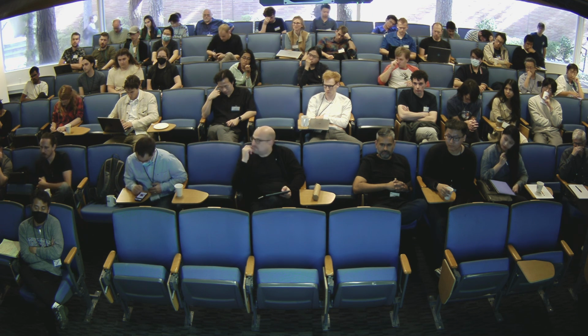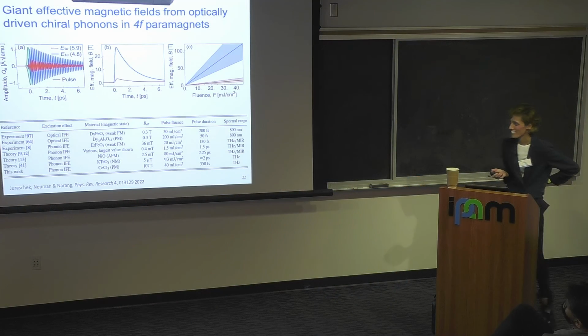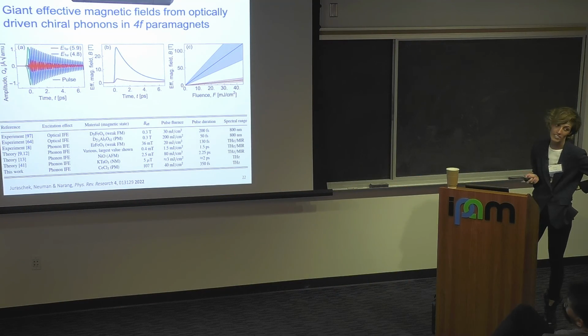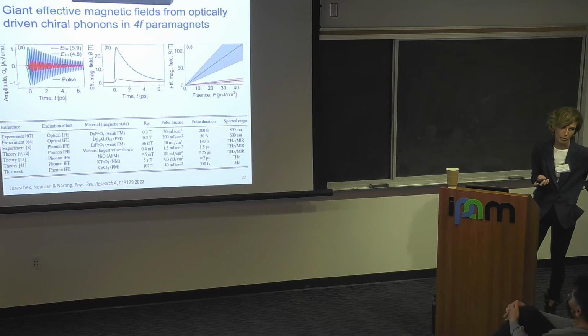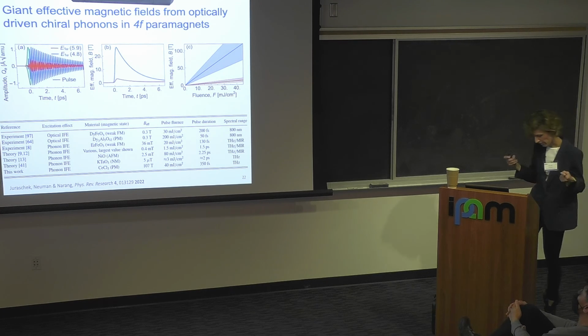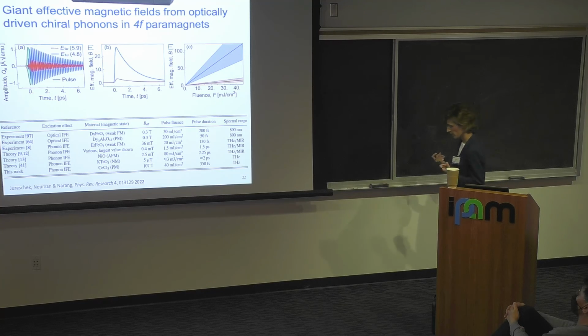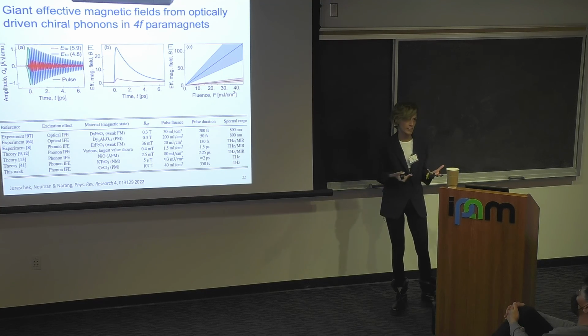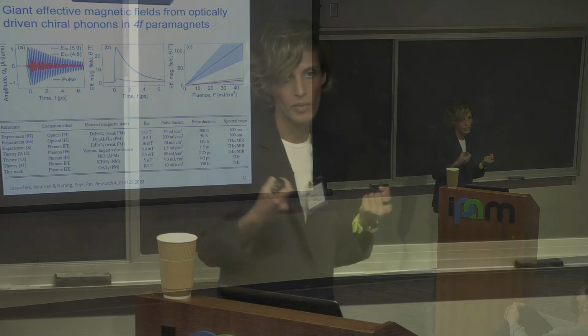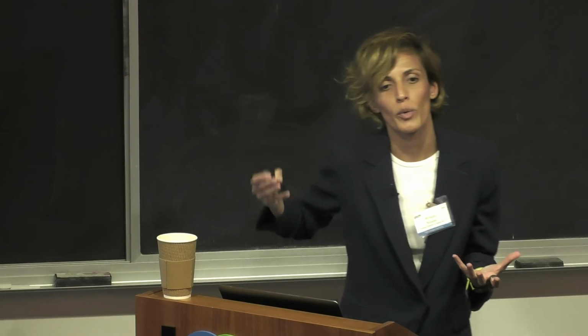Yes. What works, and how do you? So cerium trichloride, we cheated a little. We did a little bit of dynamical mean field theory. That was sufficient to figure out just the right lattice, right? Because it turns out that if you have something like density functional theory, the lattice would end up wrong, even though we're not looking at direct optical excitation, which is typically where that failure mode shows up.